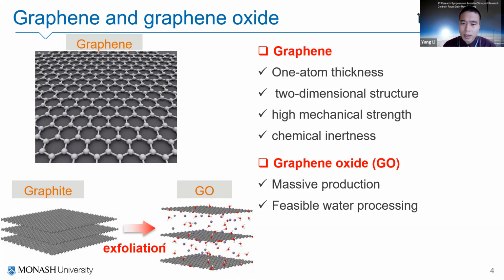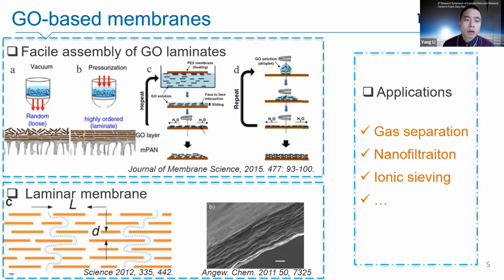Compared to graphene, graphene oxide can be massively produced through the aqueous oxidation of graphite, and it can be processed in solution, such as we can use graphene oxide to develop a new kind of membrane, which we describe as the laminar membrane or 2D membranes. Graphene oxide membrane is very easy to get. We can use pressure-driven or vacuum filtration, or we can use the dip coating or spin coating method to prepare this kind of laminar structure membrane.